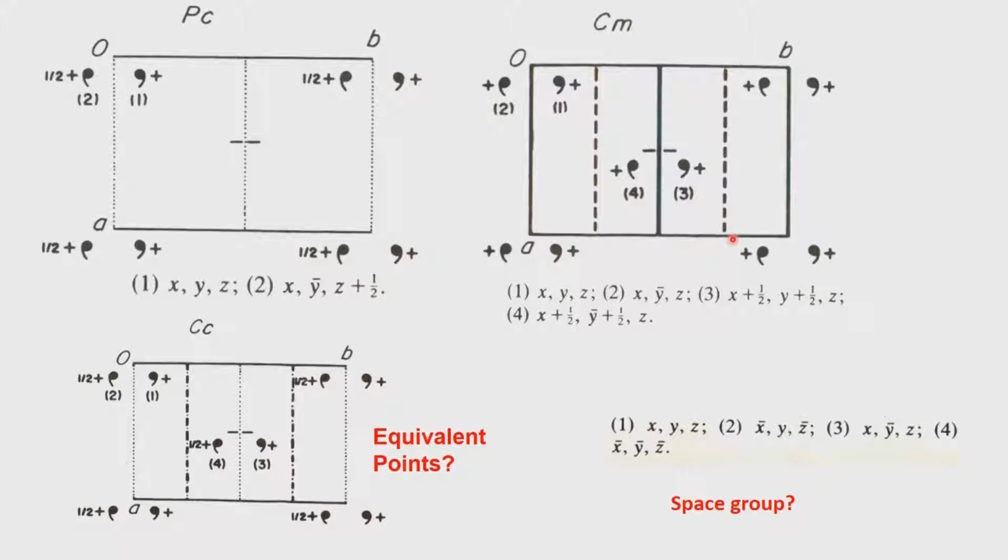And if we look at this situation where we have a C centered lattice with a C glide, then we generate equivalent points which will result in the presence of an N glide, which is at 1/4 and 3/4. So more additional symmetry elements start cropping up depending upon how we combine now the lattice symmetry with the point group symmetry. So the flexibility that is allowed now for the objects which go into these space groups is kind of restricted, because it has to satisfy the other symmetry elements which are also developing.